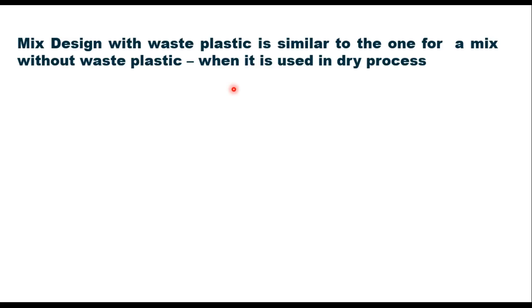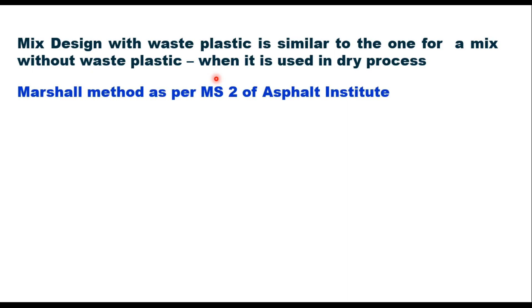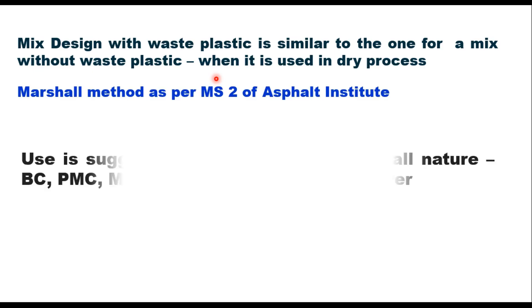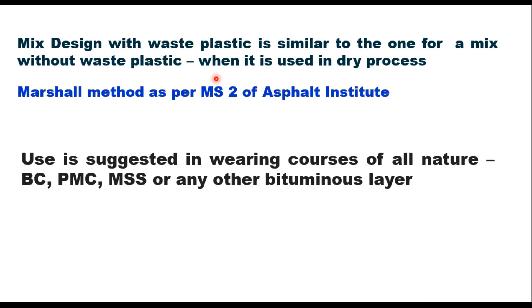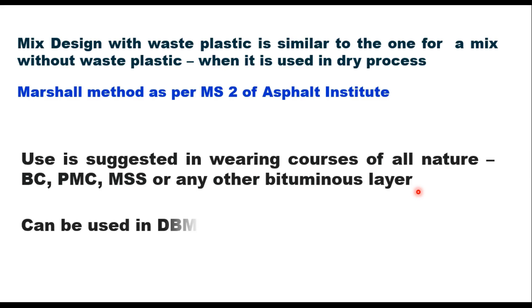IRC SP 98 2020 recommends the dry process of using waste plastic in a bituminous wearing course. When the dry process is used, there is not much difference in the mix design procedure — it is similar to the Marshall method of mix design as per MS2 of the Asphalt Institute. Use of waste plastic is suggested in wearing courses of all nature, whether for low volume roads or high volume roads. You can use waste plastic in bituminous concrete, premix carpet, mix seal surfacing, or any other bituminous layer used in the wearing course.